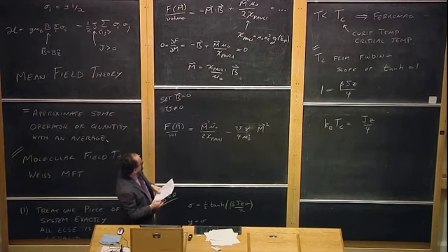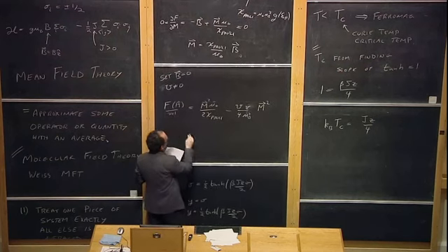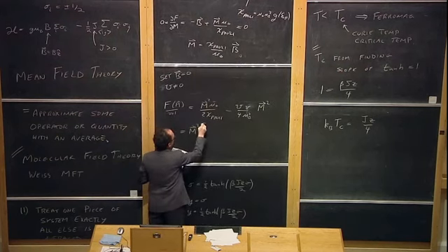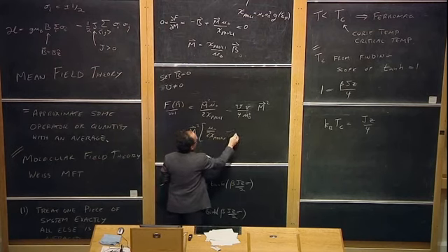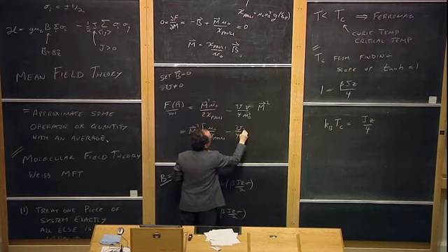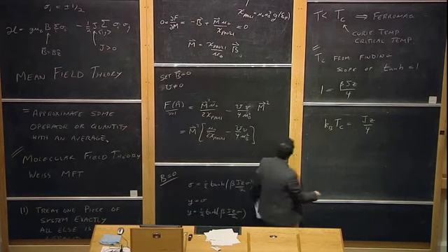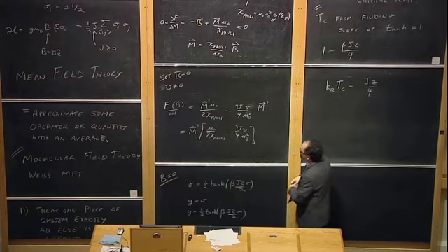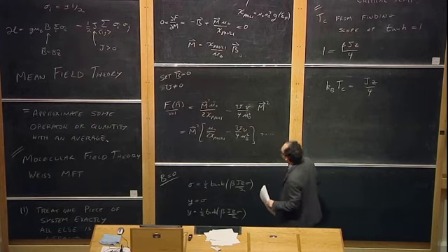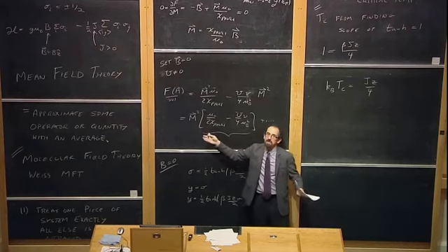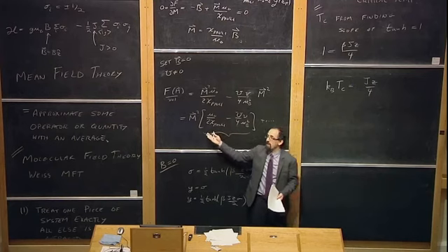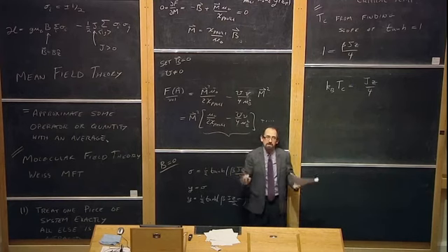All right. So what this is, I guess, we can factor out the M. So we have M squared and then mu naught over 2 chi Pauli minus U over 4 V over mu B squared. And there will be higher terms too, terms which are quartic in magnetization and so forth, which we're not interested in. But the key thing to realize here is if this thing in the brackets is less than 0, then the magnetization wants to be non-zero. Whereas if the thing in the brackets is greater than 0, then the magnetization wants to be 0.